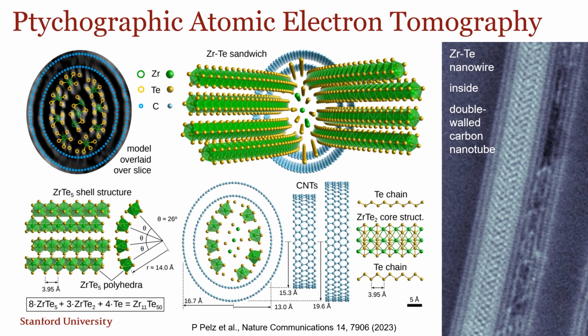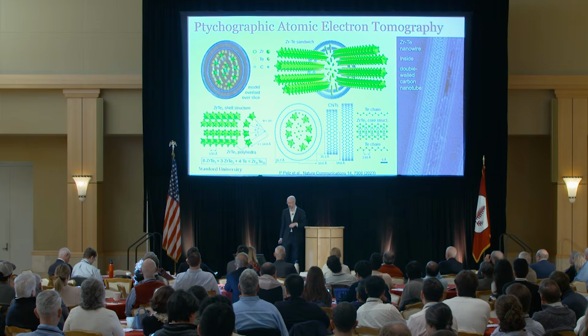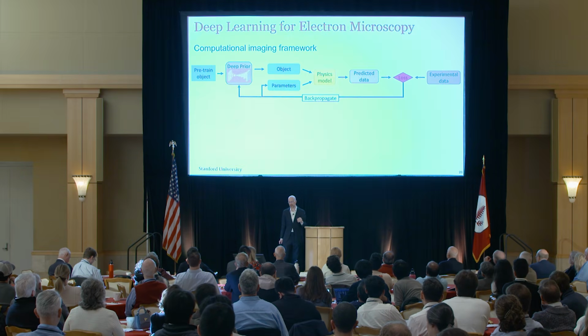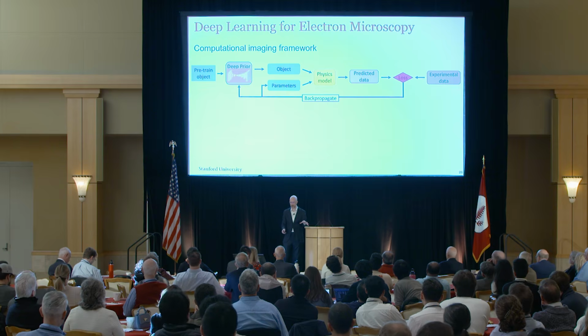The second problem is inside the nanotube, it wasn't just one crystal structure or two crystal structures. There's this distinct core and shell region, and then individual chains of tellurium atoms actually following at the top and bottom. And I would never have been able to infer what this 3D structure was from a single two-dimensional projection here. Okay, so I'm going to show two quick studies here, but now this is what we're doing now.